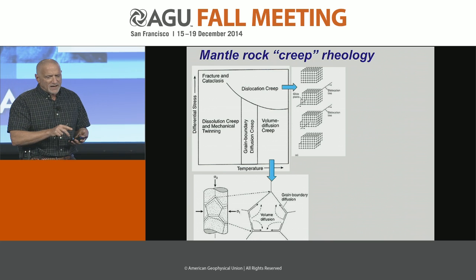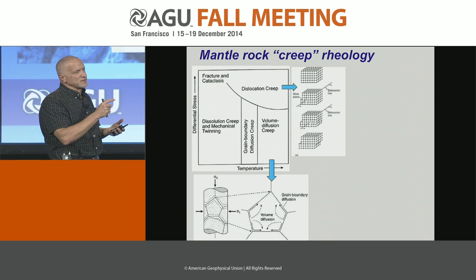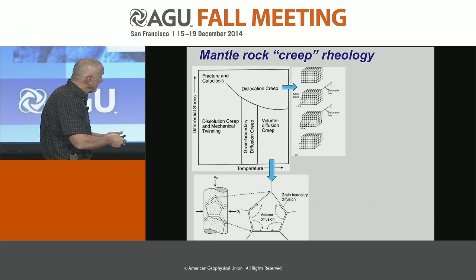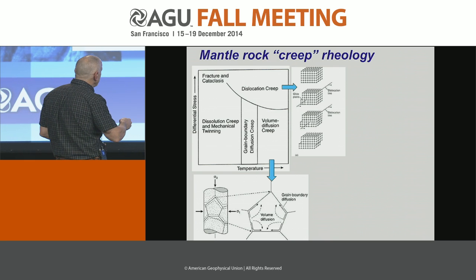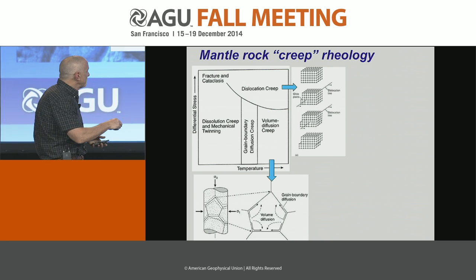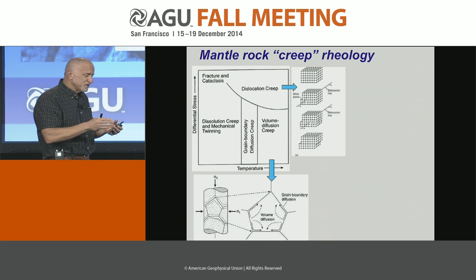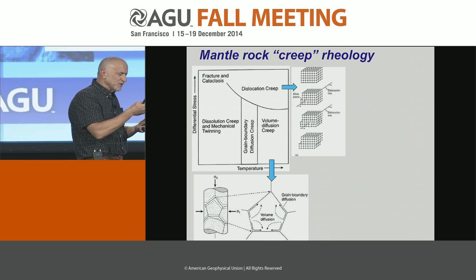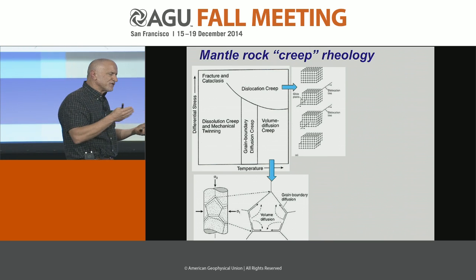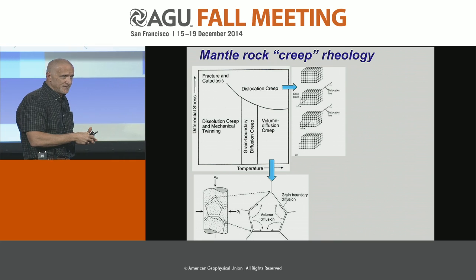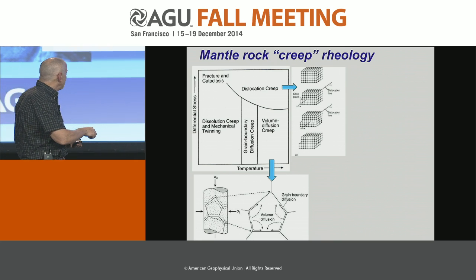In the area of the mantle that we're most worried about, they undergo this type of deformation called creep. For example, there's dislocation creep, at these mantle temperatures and stresses, where you're sliding along a dislocation, or a missing row in a crystal lattice. You're sliding along to relieve stress. Otherwise, you can have diffusion creep.